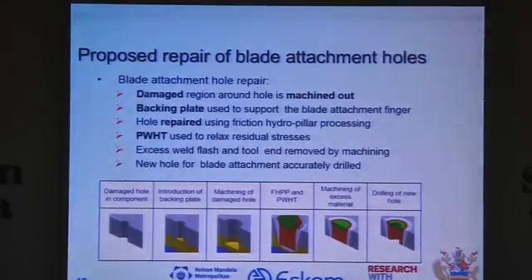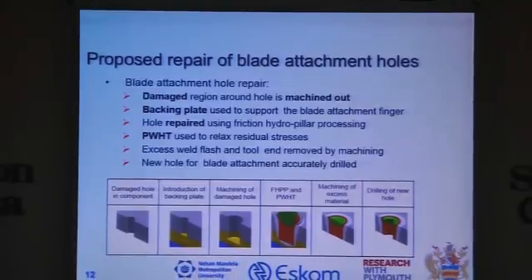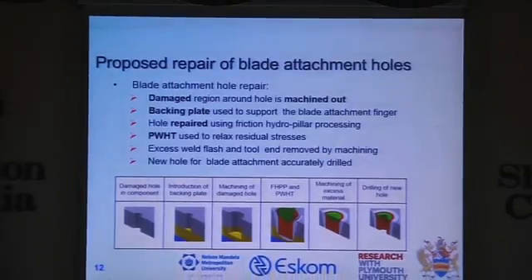So we come up with a proposed repair procedure. Conventional welding cannot be used, so we make use of friction hydropillar welding. In the first picture, we drill out the damage. Then we put in the backing plate, the yellow backing plate. We then drill down in the backing plate. The reason we go down in the backing plate is that the place for introducing defects within the process is at the interface between the consumable tool and the backing plate, so we take that area away. We do the weld, do the post-weld heat treatment, machine excess material away and drill the hole. This is the proposed solution that we came up with.